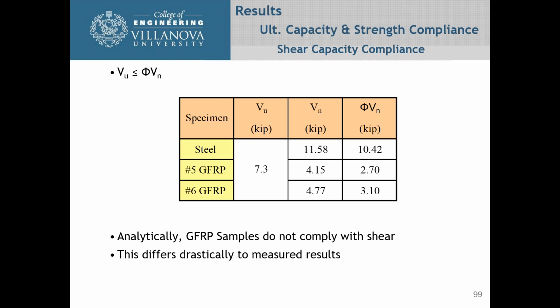Vu has got to be less than or equal to phi Vn, and the phi Vn for steel is 10.42, but for the GFRP, it's 2.7 and 3.1 respectively. So this is what the code is asking you to design for. But as you can see from our results, we were putting a lot more load on the sections, and we did not get a failure of the concrete in shear. We ended up with cracking and apparent shear failures, but did not get an actual failure where the section dropped and you couldn't take any more load.